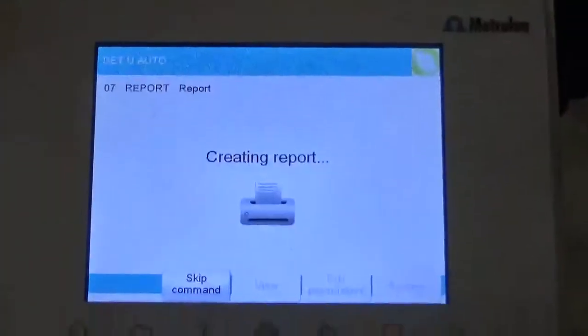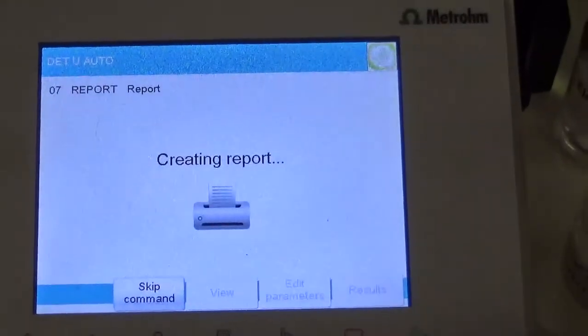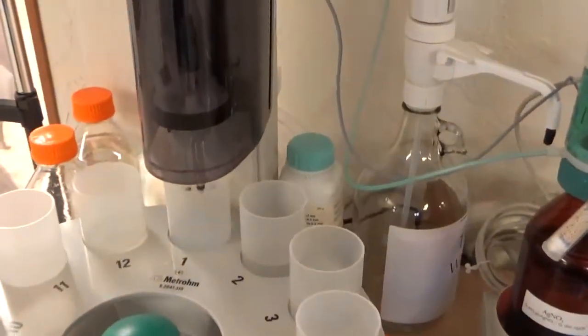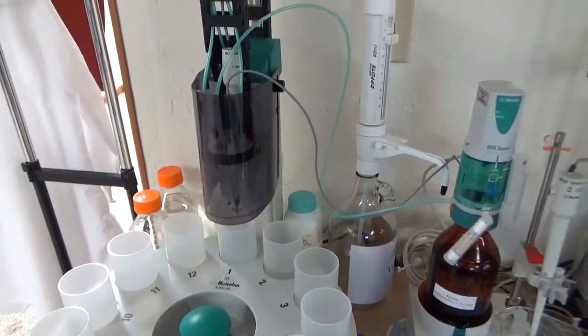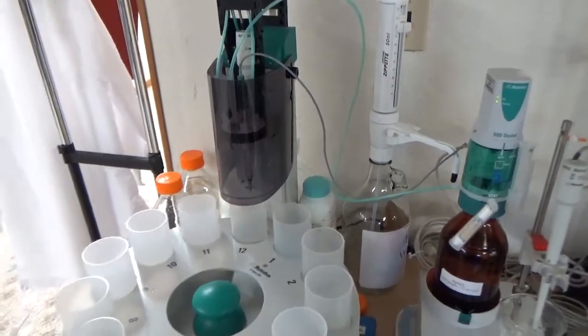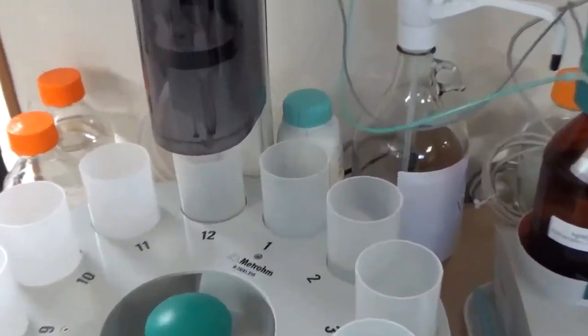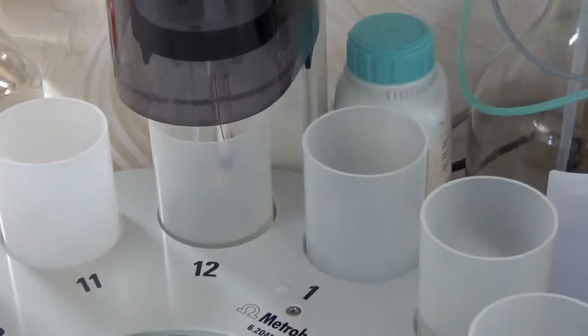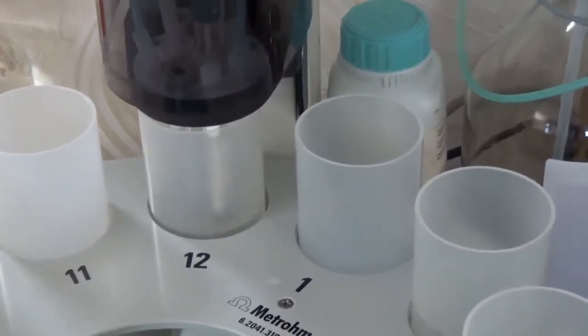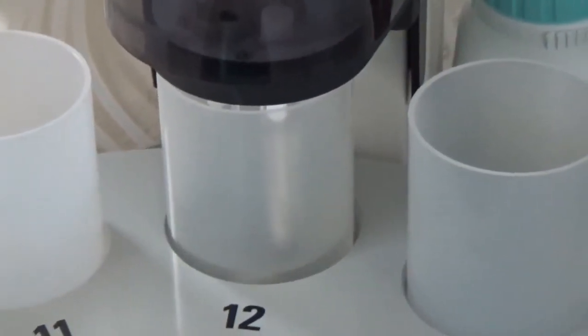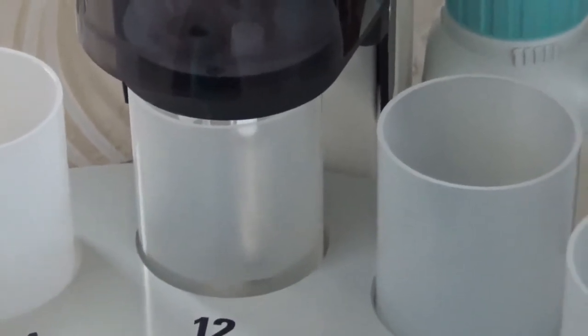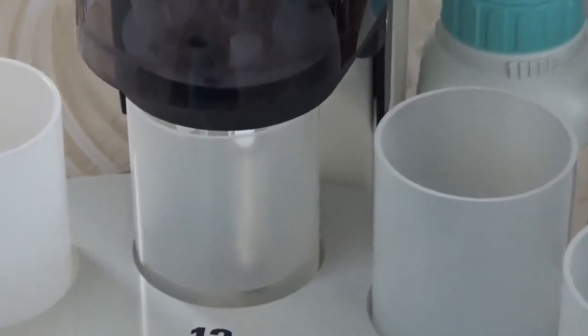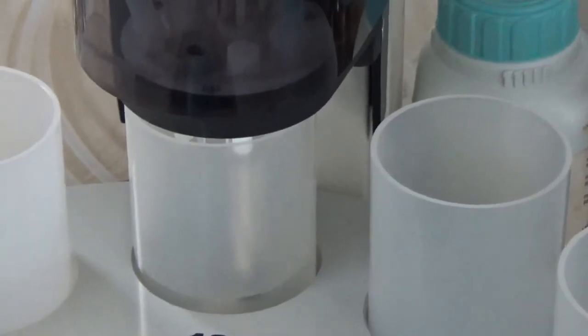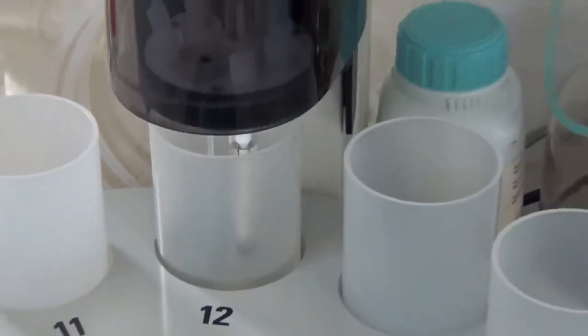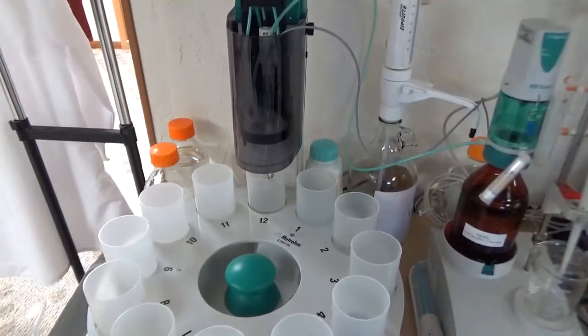So the first titration is done, it's creating the report. It will give the result of chloride content by weight of concrete. Then the tower goes up to the lift position, then it goes to station 12 for cleaning the electrode and the burette. The stirrer starts. It runs for 10 seconds to clean the electrode. Moves back to the lift position.